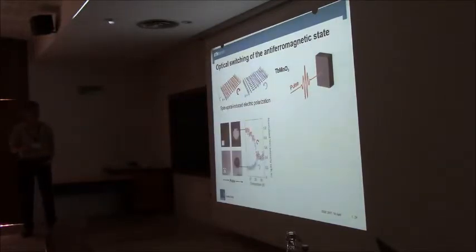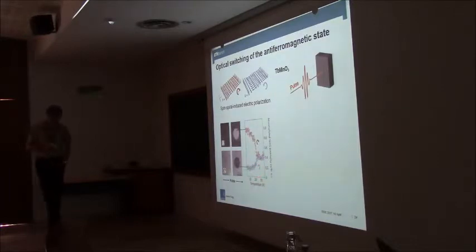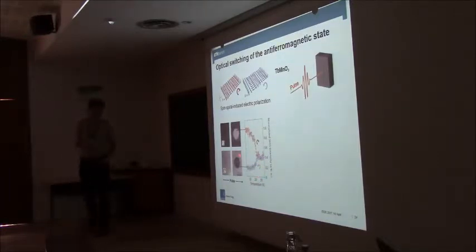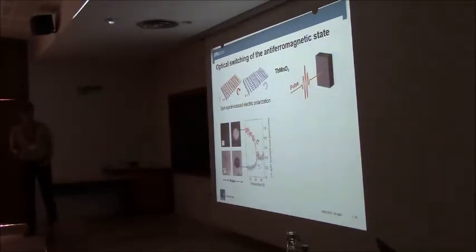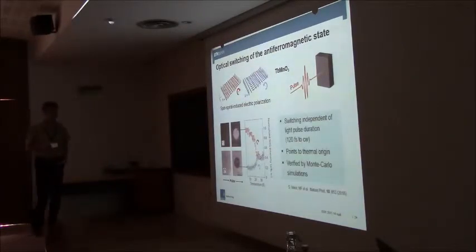That's what we got. So before and after: dark domain state, illuminated with light, it switches to bright. Bright domain state, so clockwise spin spiral, up polarization, switches to dark. And it's really not some weird effect, so when you then measure this area as a function of temperature, exactly at the ordering temperature of this multiferroic, the splitting disappears. How does that work? Well, that's pretty simple. It's a heat effect.